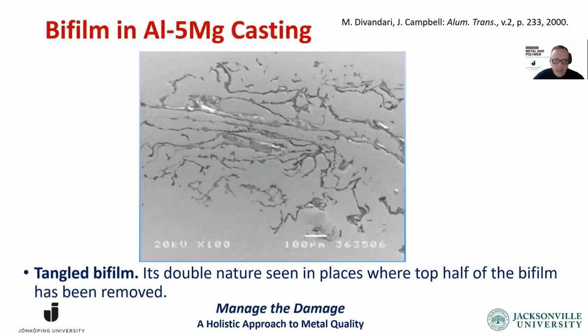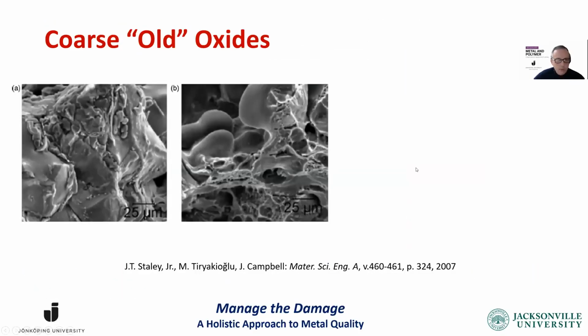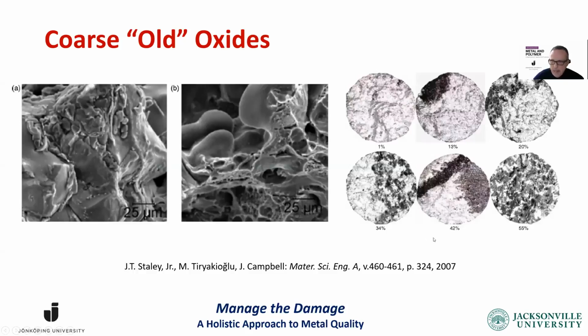Here we see a highly tangled bifilm. We can even see one of the layers that shine through. But there are many, many examples of this. I'm going to show a few. These are coarse old oxides that come from the crucible, where the surface layer has been transported into the main body of the casting. And when you look at it under the optical microscope of a tensile specimen, this is what you see, black areas. These are coarse oxides.